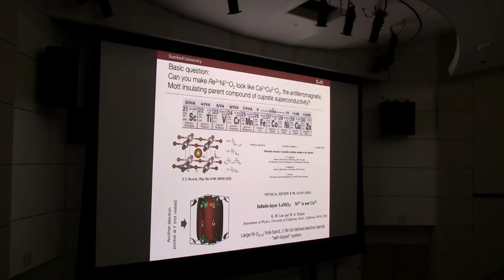And so this is a density functional calculation from this paper in the uncorrelated limit. And what they find is that there's a big hole-like Fermi surface, and this looks very much like that of the cuprate problem, coming from this orbital hybridizing with the oxygen 2p states. But in addition, there was this other different feature, these little electron pockets. There's one in the zone center here, which is derived from hybridization between the lanthanide 5d state and the nickel 3d state. So this is a little bit different.